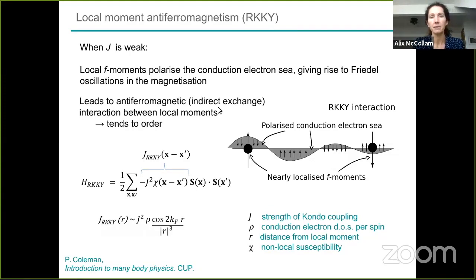It's antiferromagnetic exchange. It's indirect exchange between the local moments via the conduction electrons, and this tends to lead to antiferromagnetic order. I've taken this introduction from Coleman's very nice book. This is the Hamiltonian for the RKKY interaction, and this is the J term here for the RKKY. This J is still the strength of the hybridization between the conduction and the f-electrons, and these are the other quantities. This is distance, so this gives you the oscillation as a function of distance as you go away.